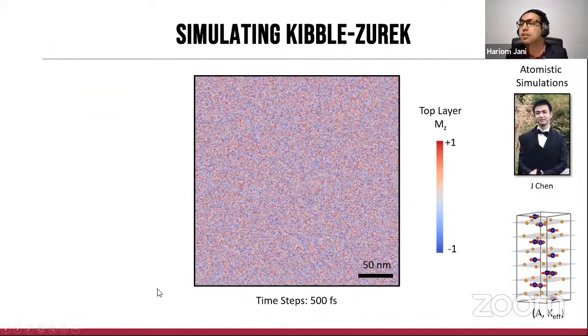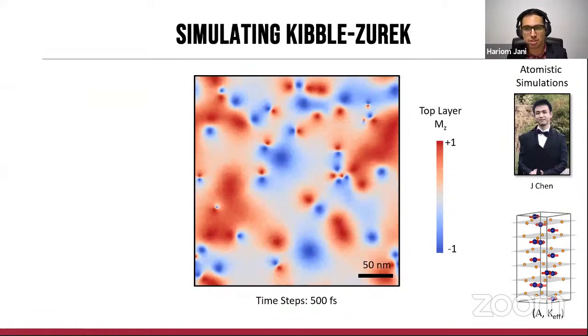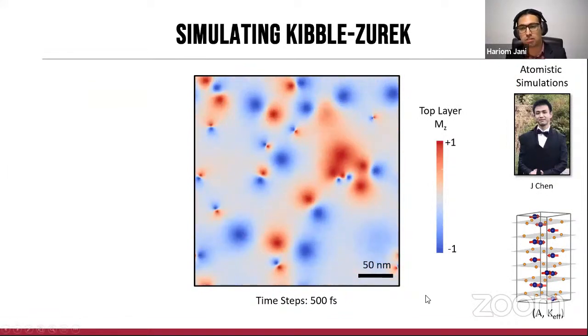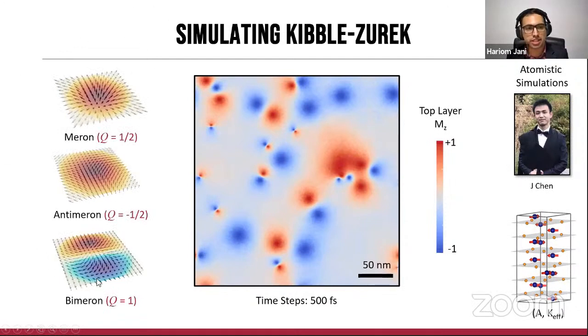So as you can see here, originally it's completely disordered, and as the system undergoes the phase transition, we start to see emergence of magnetic order until we evolve the system and observe a rich mosaic of variation of the textures. The predominant background is, of course, in the plane because it has the easy plane state in the configurations that we're looking at. And there is still some presence of out-of-plane orientations, which really corresponds to the textures that I had shown in the beginning. Some consist of out-of-plane cores, which could be merons or antimerons of different orientations that are blue, and some of them are even pairs, as seen in some of these configurations, which could either be bimerons or topologically trivial pairs, which we will look at subsequently.